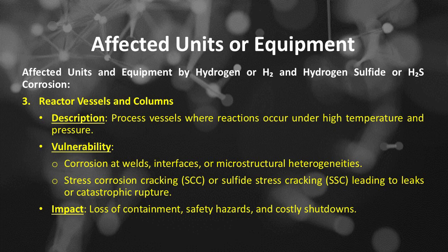The number 3 of the commonly affected units and equipment by high-temperature hydrogen or H2 and hydrogen sulfide or H2S corrosion is reactor vessels and columns. Process vessels where reactions occur under high temperature and pressure. The vulnerability of reactor vessels and columns includes corrosion at welds, interfaces, or microstructural heterogeneities, stress corrosion cracking, SCC, or sulfide stress cracking, SSC, leading to leaks or catastrophic rupture.